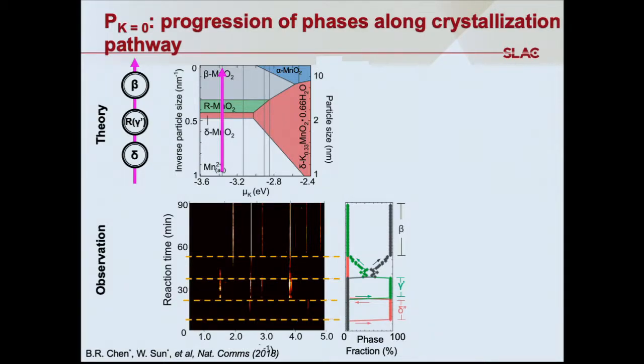Then they form gamma, but gamma is essentially a slightly disordered version of Ramsdellite, so I still count it as a 90% win. And then they form beta, beta MnO2, the pyrolusite. So really good. So the phases that form in sequence are essentially the ones predicted by sequential nucleation, right? So this is a case where clearly theory can actually tell you what forms and in what sequence, right?